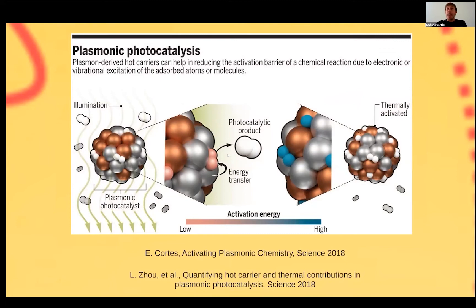The new thing is that quite recently it has been shown that plasmons can create electron-hole pairs during plasmon decay that excite molecules into the excited state and lead to new potential energy surfaces for new reactivity. Importantly, plasmons can be excited with continuous-wave lasers in the visible regime — conditions much closer to sunlight-driven chemistry than before. For this reason plasmons have received quite a lot of attention recently.